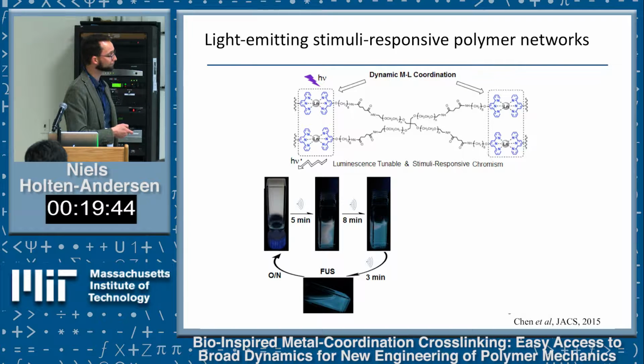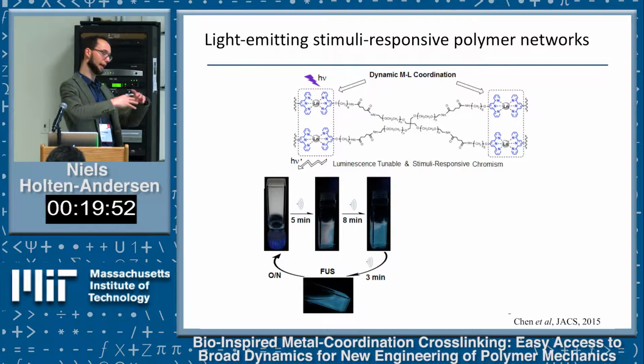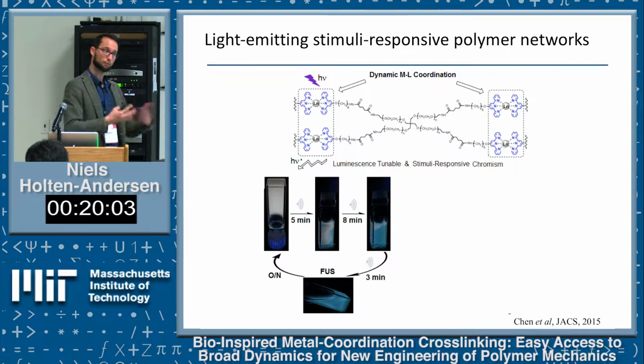We sonicate it in a sonication bath, the gel network breaks up and turns into a fluid - a blue emitting fluid - because the free polymer, once unbound from the metal ions, is this blue emitting polymer. So we've ripped the metal ions out of the network, we have a blue emitting fluid, and we let it rest overnight, and it self-assembles back into a white light emitting gel. So it's self-healing, but it also changes color as a function of when you break the material.